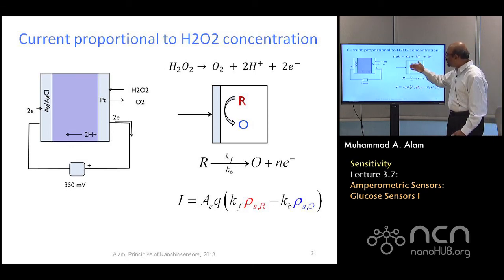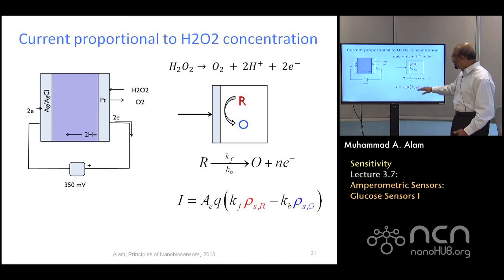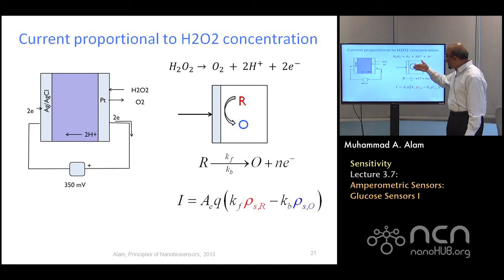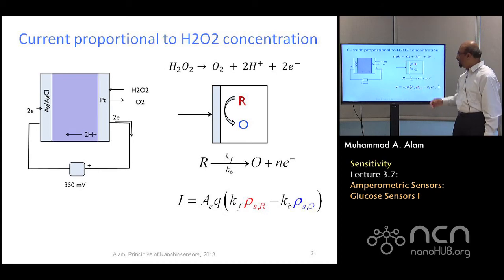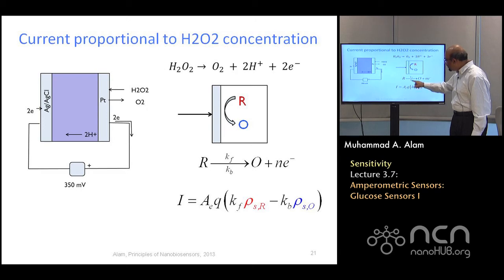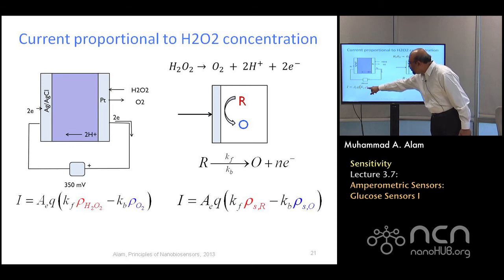Of course, it depends on the exact voltage that you have applied. In this case, the net current that flows is proportional to the forward reaction, giving electrons, and the reverse reaction, taking electrons back. The difference of the two, multiplied by the area of the electrode, gives you the current. And of course, it depends on the voltage also. The voltage, let's say 350 millivolts here, determines kF and kB, the forward and backward reaction rates. Specifically, in this case, we have hydrogen peroxide and oxygen. These two are R and O in our case, and that will determine the current, provided the 350 millivolts dictates kF and kB.